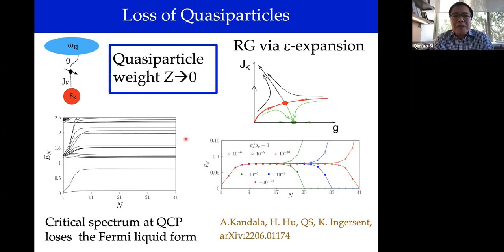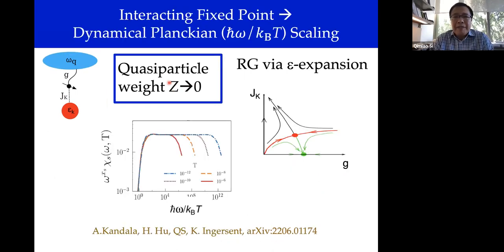So for this Bose-Fermi Kondo model, one can do more. For instance, one can calculate the finite size spectrum. This is a collaboration with Kevin Ingersent's group, with a particular one of these models, where this red line describes the finite size spectrum at this red fixed point. If you move away from the red line here, you go to a different spectrum, and eventually the spectrum can be described by a Fermi liquid form. But at this red fixed point, this finite size spectrum, just at the quantum critical point, loses the Fermi liquid form entirely. And that's a characterization of the quasi-particle weight going to zero.